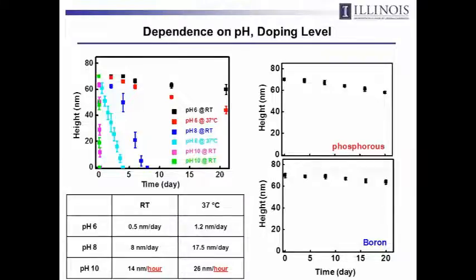There's also a strong dependence on pH. As you go more and more basic, the rates of dissolution go up. So you're a little bit acidic here, mildly basic, a little bit stronger basic conditions, and you can see what happens to the rate. 1 nanometer per day, 15 nanometers per day roughly, to 25 nanometers per hour at a pH of 10. So very sensitive to that.